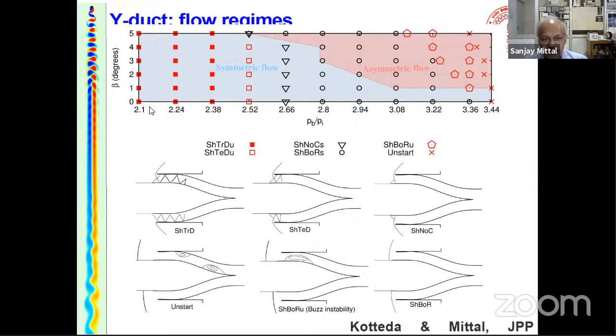So one can get a picture of the back pressure ratio on the x-axis, the side slip angle on the y-axis, and then try to figure out what are the different flow regimes that one can get. So just to cut a long story short, at low back pressure ratios you can have this shock train, they become stronger as you increase the back pressure ratio. Then you can get this lambda shock, followed by the bow shock standing outside the inlet. And then you can get a region of separation.